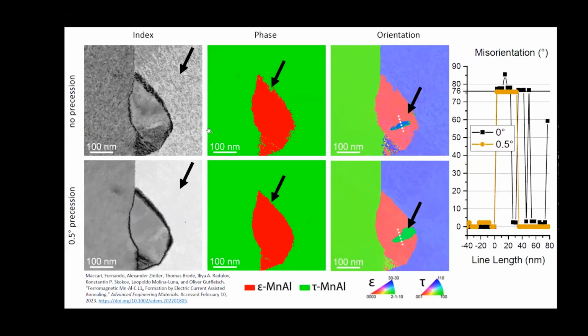in the software interface. So I will actually go back to one slide that shows this data set quite well. Let's just maximize this. And here you can actually see the difference between using precession electron diffraction and just the same data set acquired with the precession turned off. So on the top row, you can see the data set with precession turned off, and immediately see what you can see here in this index map, which is kind of a measure of how easy it was for the template matching routine to attribute a template to the recorded diffraction pattern. You see a lot of noise. So the software was not really sure on which template to use. Or maybe it could not decide between different orientations of the crystal of what to match.